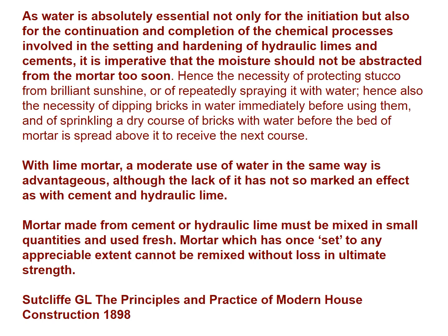With lime mortar, by which Sutcliffe means an air lime mortar or a feebly hydraulic lime mortar, a moderate use of water in the same way is advantageous, although lack of it has not so marked an effect as with cement and hydraulic lime. Mortar made from cement or hydraulic lime must be mixed in small quantities and used fresh. Mortar which has once set to an appreciable extent cannot be remixed without loss in ultimate strength.